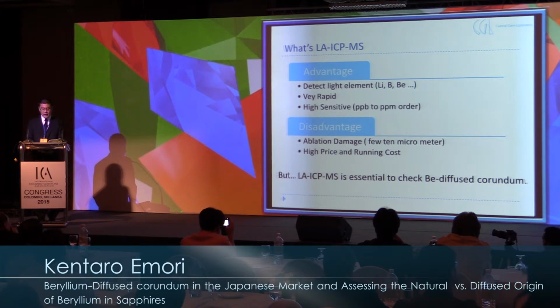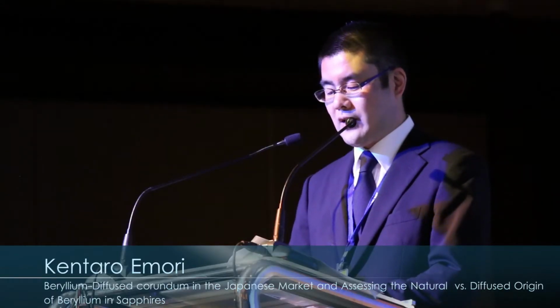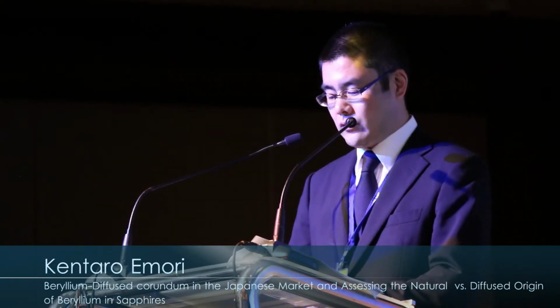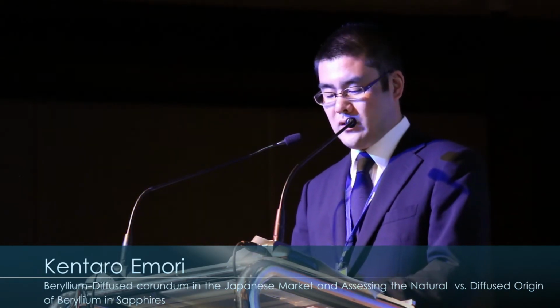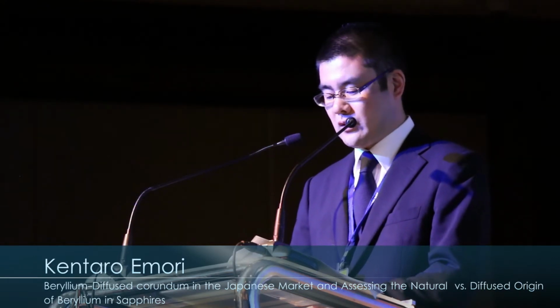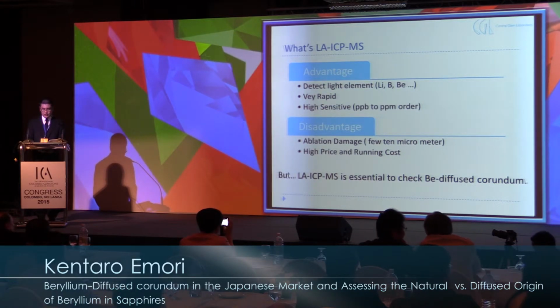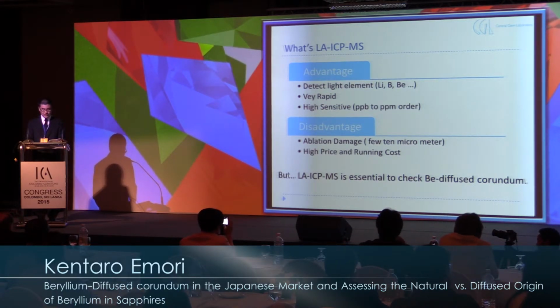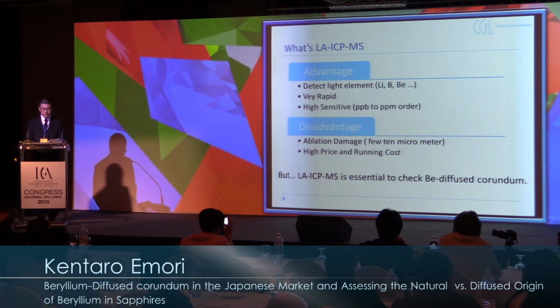The summary of LA-ICP-MS is as follows. At first, it detects light elements such as lithium, boron, and beryllium, and analyzes very quickly. One-point analysis takes a few minutes and it is easy to change samples. Second, it can analyze elements in ppb to ppm order, but this instrument has two disadvantages. One is ablation damage of some 10 micrometers, and the other is that the running cost is high because we use argon and helium.